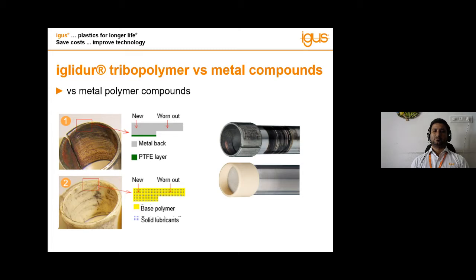First one being the PTFE coated metal rolled bearing. This is a very common part that most of our customers would have come across. The main technology of these parts is a small 30 to 40 micron Teflon layer. In the drawing, you can see the green colored part is the Teflon layer, on a backing material that is usually bronze or iron. Once the Teflon coating is worn out after a few thousand cycles, the coefficient of friction will gradually increase once the metal backing starts, and you will have complete damage on the shaft, with scoring marks because of the increased friction.